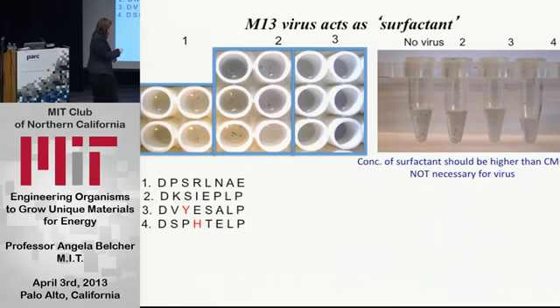And then they put them in these little dialysis chambers, and then they try to see which ones would precipitate out. If they precipitated out, they weren't acting as a good surfactant, because the carbon nanotubes were collapsing and coming together. But if they stayed in solution, then we had a chance. And so they found a couple of clones that would keep the carbon nanotubes solubilized.